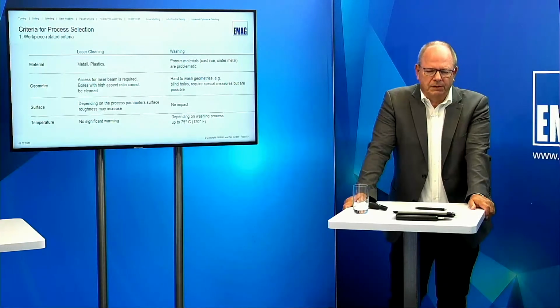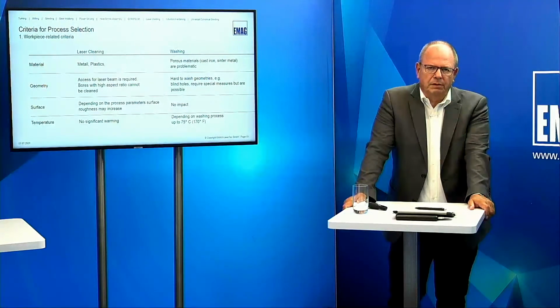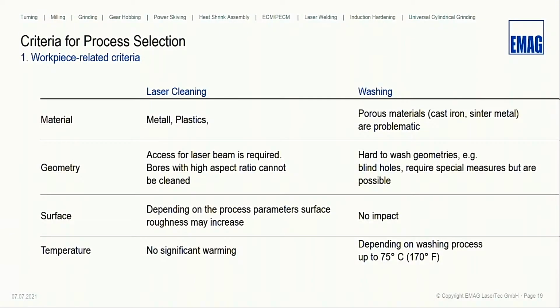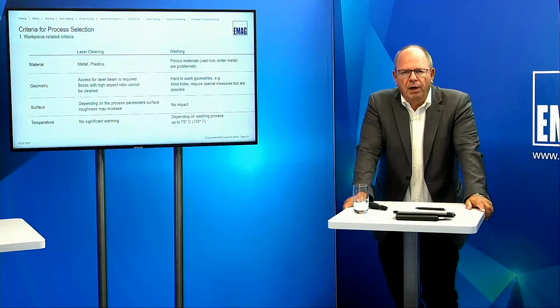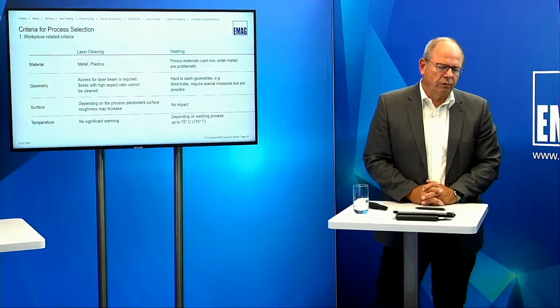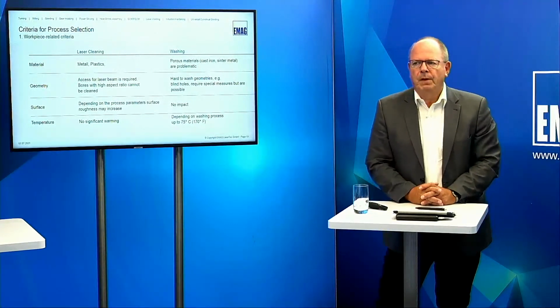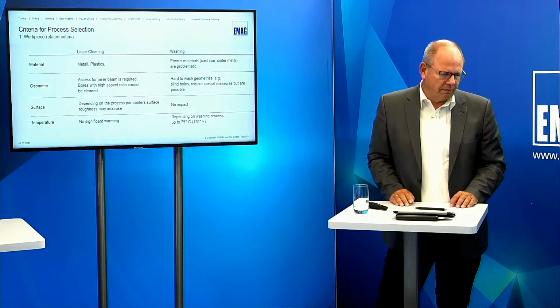If it comes to washing, I would say typical industrial materials, cast iron is hard to wash. We see that. Sinter metals is even worse because of the porosity. There is some oil always sitting in the material, and you wash, but it doesn't get clean. So from the material standpoint, I see a clear plus for the laser cleaning. Geometry, laser cleaning is a little bit demanding in that we need access for the laser beam. So inner contours, bores with a certain aspect ratio are not possible. These difficult geometries cause also problems in a conventional washer, but usually you find a solution. Not always, but usually you do. So I would say washing has some plus more points than the laser cleaning at this side.